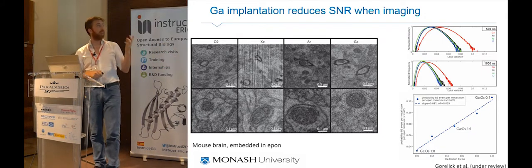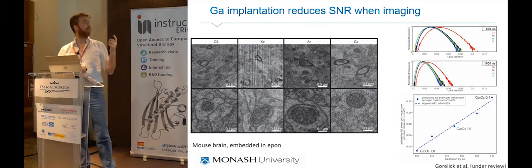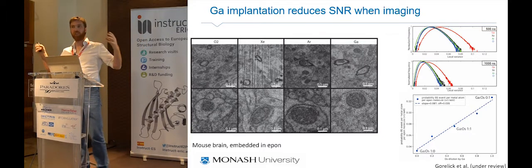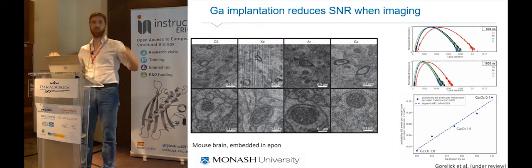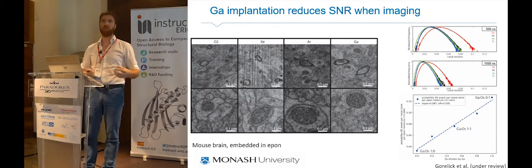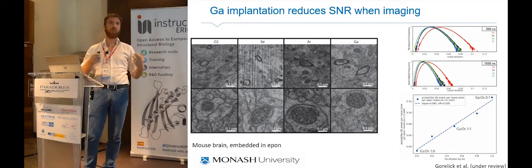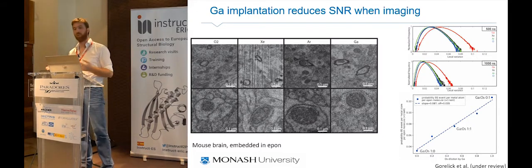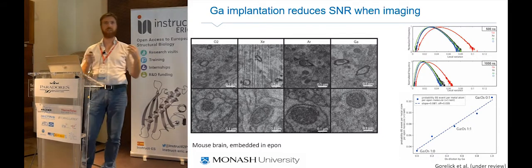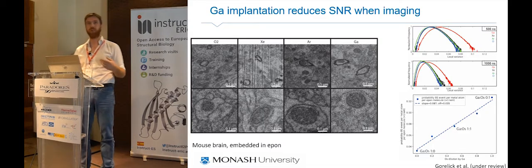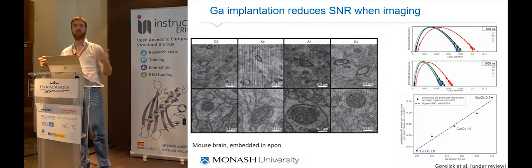So this is actually really interesting, because if somebody's interested in taking very large volumes, and you're not interested in resolution, you shouldn't be using a FIB. You should be using a slicer, roughly, or a plasma FIB eventually if you've got one, because you will increase your throughput by 30% roughly, just because you can image much faster and have the same level of noise.